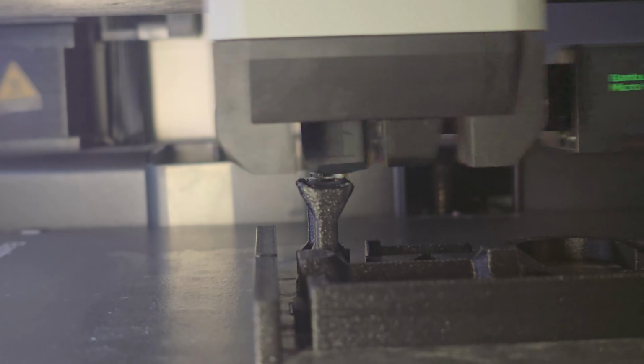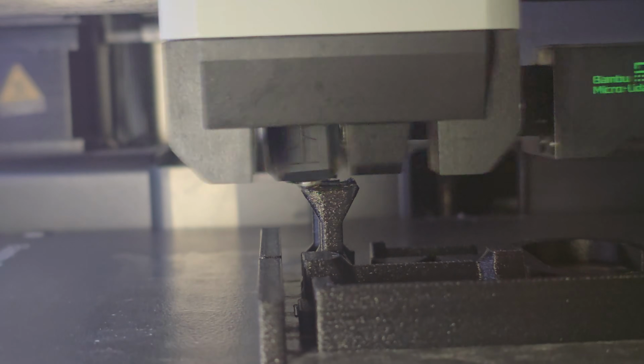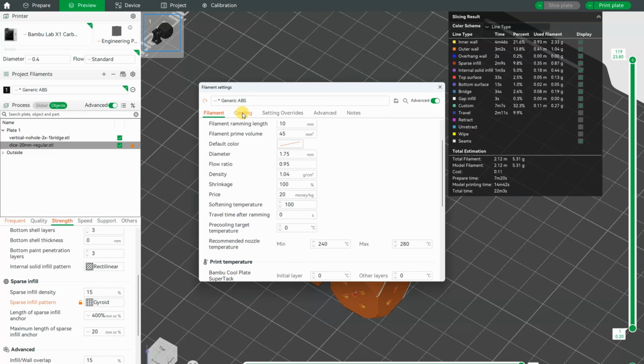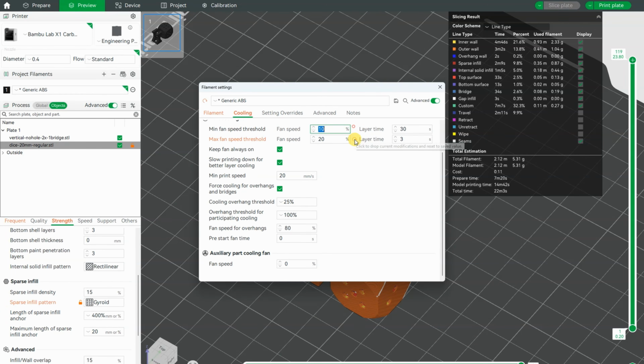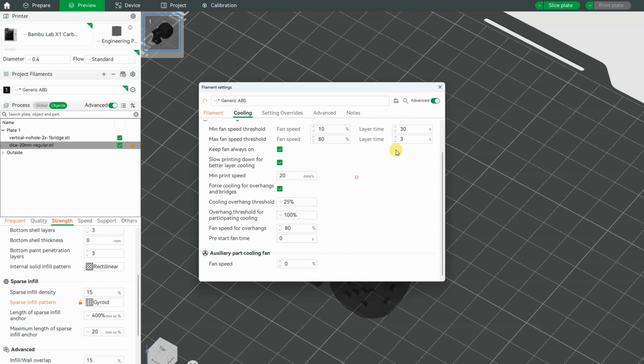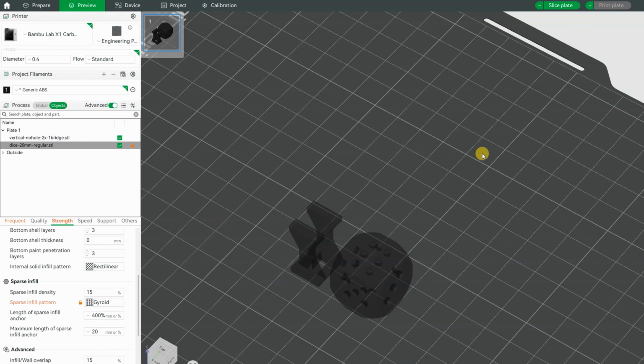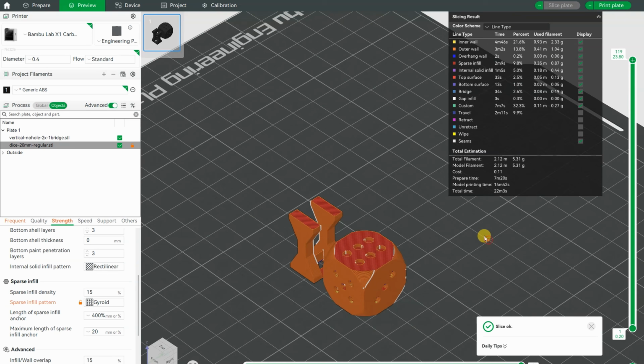Now I can see on these vertical test objects for the layer adhesion that this curling up starts to be too much. The part cooling is a little bit too low. Those 20% are not enough. Layer adhesion test objects I am reprinting with the default part cooling, which is maximal 80%. And I will have these 6 dice to have more time for the layer to cool down. I think they look much better now, but I will analyze them later.